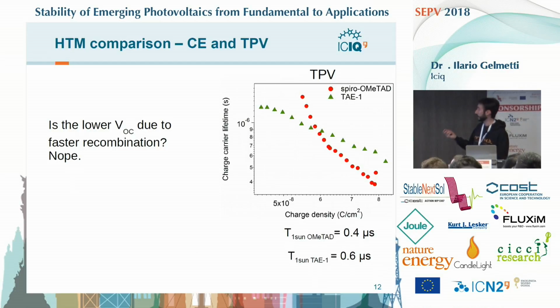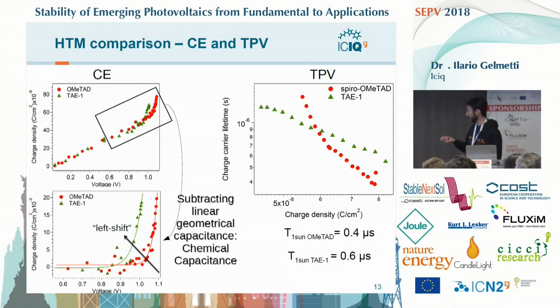Okay, so we used the transient photovoltage for studying the recombination. And we saw that the lifetime obtained from the spiro-OMeTAD is even smaller than the one obtained from solar cells with the new hole transporting material. So that's not the reason for a lower open circuit voltage. Then we observed the charge extraction, and the first part just says that the thicknesses are the same, okay, not interesting. The exponential part, which is enhanced here, showed a shift in an unexpected direction.